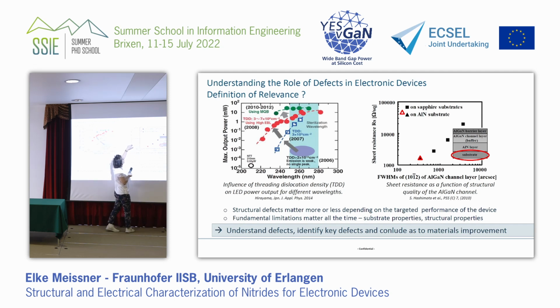A good example is what the quality of the substrate determines. You see as an example the sheet resistance in a HEMT device with an AlGaN channel, and the quality of the AlGaN channel is expressed in terms of full width at half maximum. The full width at half max is smaller here, larger here, and you have these points where the sheet resistance we want to achieve would be in these regions, so it should be small, and the number of dislocations should be small. If we have a better device, like this triangle, it means the full width at half max is smaller, so structural quality is better, and we have the targeted sheet resistance.